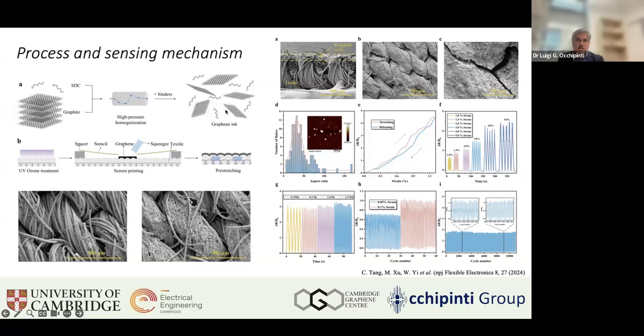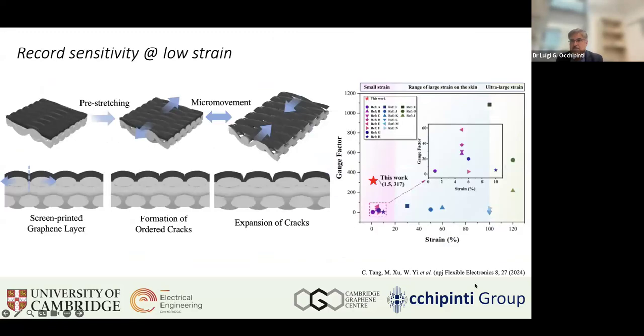Again, we exfoliate graphene from graphite. In this case, I think it was artificial graphite, then deposited with a screen printing process, and then tested as a strain sensor and already embedded in the textile structure. So this work was published in npj Flexible Electronics earlier this year. This explains the mechanism of the microcracks that we investigated in this work, and also the characteristics in terms of strain sensitivity. Why are we interested in this area?